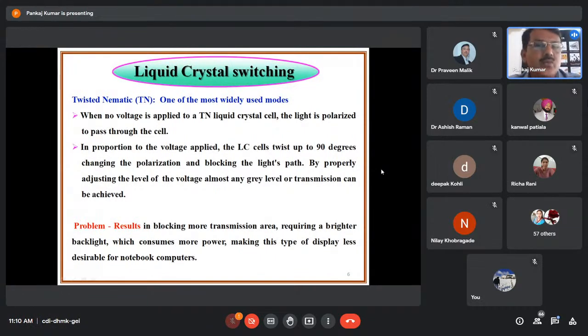However, when we apply the voltage, the liquid crystal cell twists up to 90 degrees, changing the polarization and blocking the light's path. By properly adjusting the level of the voltage, almost any gray level or transmission can be achieved. But in the case of twisted nematic, it results in blocking more transmission area, requiring a bright backlight, which consumes more power, making this type of display less desirable for notebook computers. So we need to move to some other modes to improve these drawbacks of the twisted nematic display.